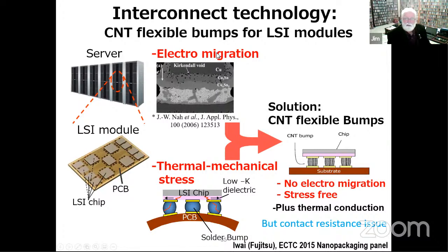And this one, the electron migration, is creating a problem as we go down in size with solder joints, because the electron migration that we saw in integrated circuit interconnect on chip in the past, now it's rearing its head because basically if you go through the theory, the higher molecular weight of solder and a couple of other properties means that solder will permit electron migration at about 2 orders of magnitude lower current densities than aluminum or other normal IC interconnects. So it's a packaging problem with solder.